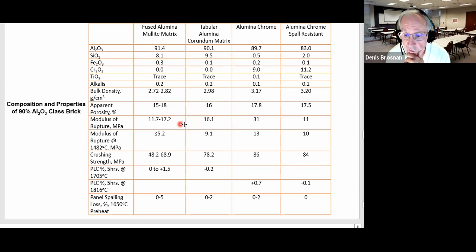Specifically, you'll see a lot of differences in modulus of rupture. So the lower the silica content with a higher alumina matrix, we're going to get more direct bonding. We're going to have higher modulus of rupture. Of course, that's especially true at elevated temperature. We can have very high crushing strengths with these particular products, and permanent linear change, PLC, that's the shrinkage on reheating, in this case to 1705 degrees Celsius. We get very little or no shrinkage, particularly in the one with tab alumina.